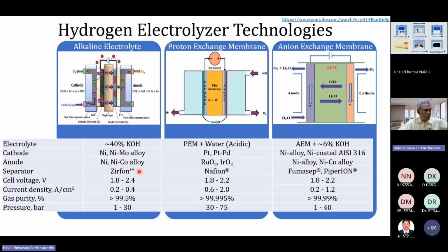Coated. The membrane, which is again a polymeric membrane that takes care of the system, and the operating voltages, current density. You could see that at low current densities, the yields can be lower, it operates at relatively low pressure, and the purity levels are on the lower side. This is after doing a bit of deoxo, so oxygen removal and a bit of removal of the alkali products. Typically done with the highly alkaline chemistries. 6 molar, 8 molar hydroxide chemistries, typically operated at slightly higher temperatures as well.